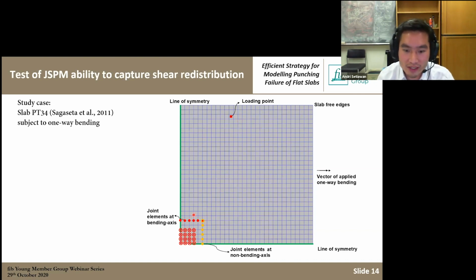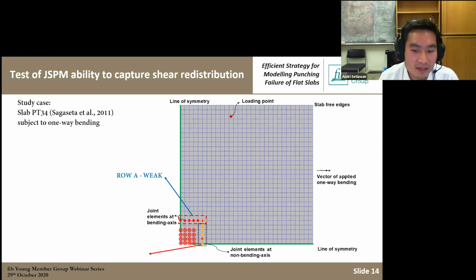We can imagine that for these joint elements in here, this will be weaker because the rotation in this part will be higher, which means that the resistance will be less. Whereas in the yellow part of the joint, we have smaller rotation, which means that the shear resistance will be higher. So with this case study, we want to show how shear force can redistribute from the red dots to the yellow dots.